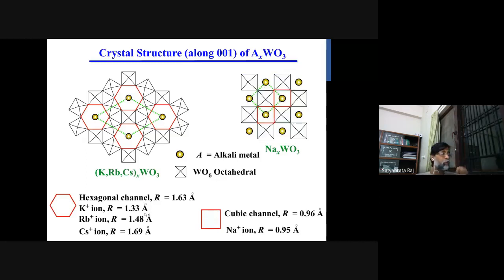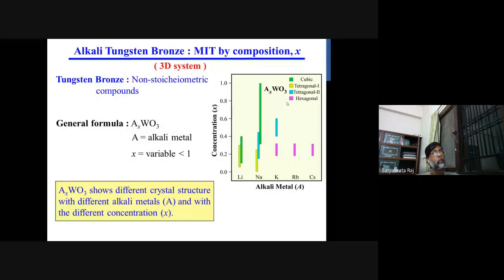If you put potassium, rubidium and cesium, their ionic radius is much more than sodium, which cannot be accommodated in cubic. So that is why it goes to a hexagonal structure and it stabilizes there. So that is why, if I go back, potassium, rubidium and cesium crystallize in the hexagonal phase, and as you reduce the atomic radius, it stabilizes in the cubic phases.